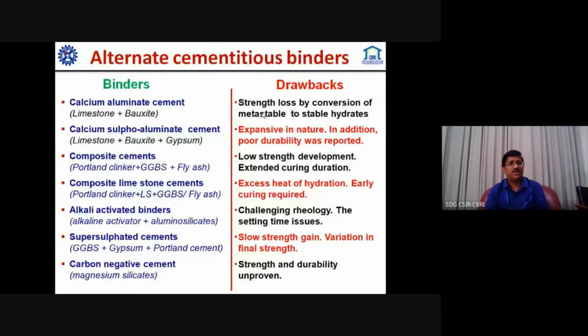Also, work has been carried out on calcium sulfoaluminate cement. It has also been very good, but due to some free lime and other things, it has been observed to be a little bit expansive in nature, and additionally poor durability was reported. But we are continuously working to improve, like composite cement, for which our Indian standard already came up in 2015, where we are going with Portland clinker and more than 50% utilizing GGBFS and fly ash. So only some issues have been observed, that initial strength development is lesser, but after 56 days it is comparable with the OPC, and some curing durations will have to be enhanced.